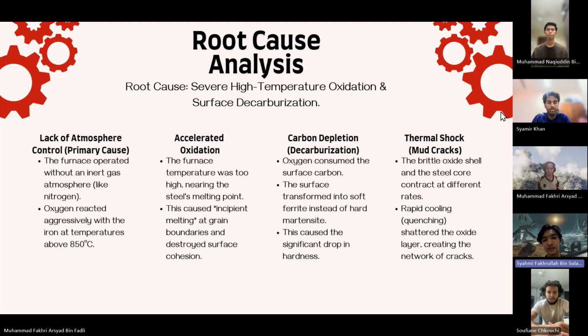And lastly is the thermal shock, which can also be called mud cracks. So the brittle oxide shell and the steel core contract at different rates, and when rapid cooling or quenching occurs, it shatters the oxide layer and creates a network of cracks.